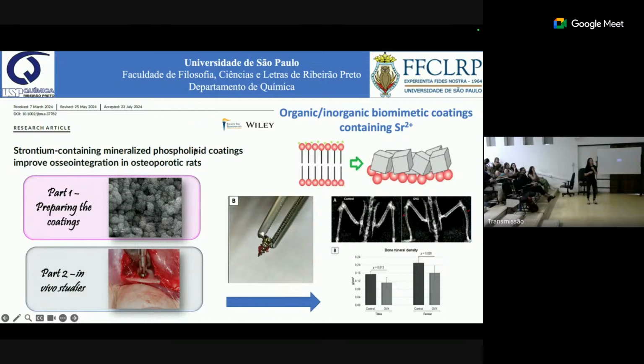paper that we recently published in collaboration with Skell and Professor Owen. In this study, we coated the surface of these mini implants using these lipid films, and we transferred calcium and strontium to the surface of the lipids. Then we mineralized the samples after the contact with a calcium phosphate buffer and a simulated body fluid. We implanted these mini implants in the bones of an osteoporotic rat model in collaboration with colleagues from UNESP Araçatuba.